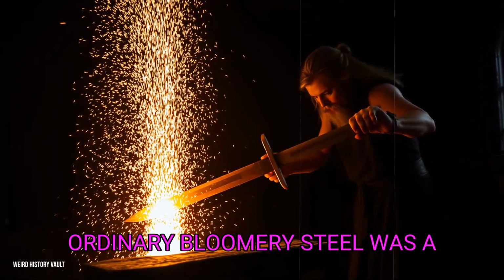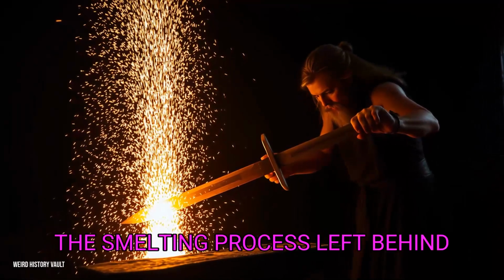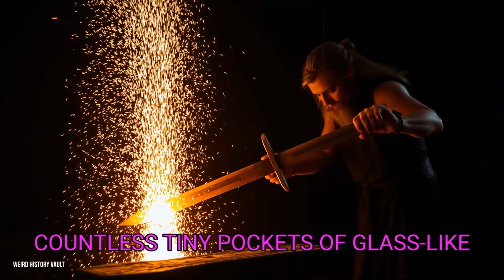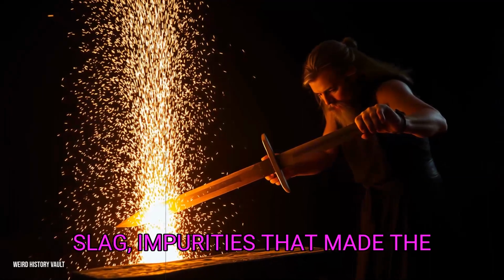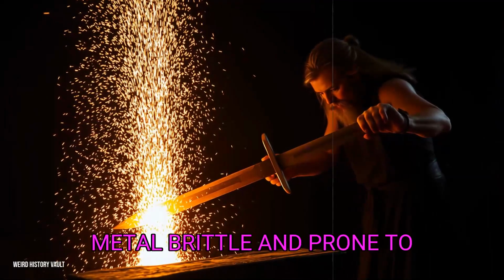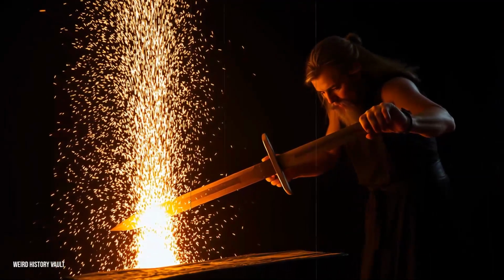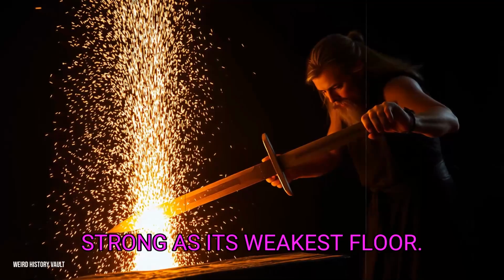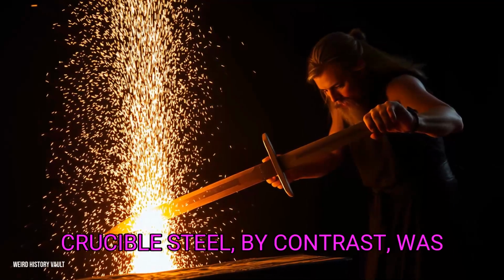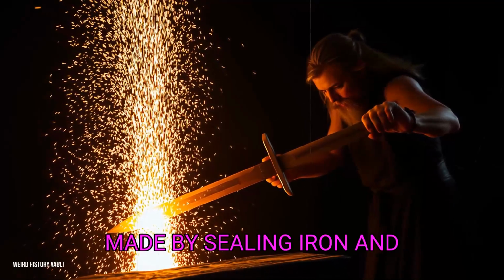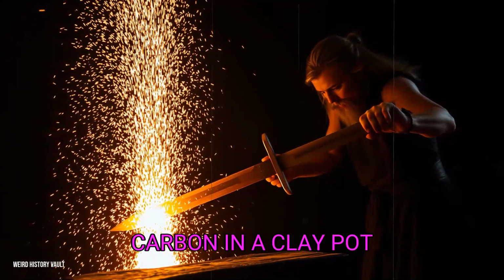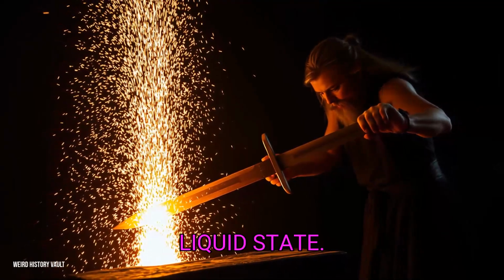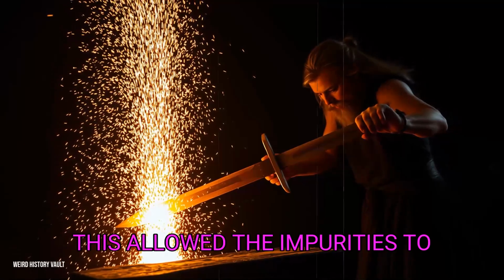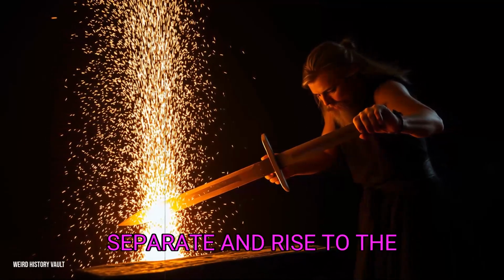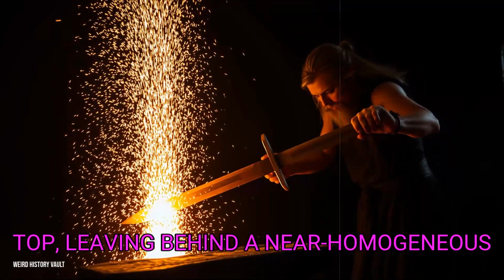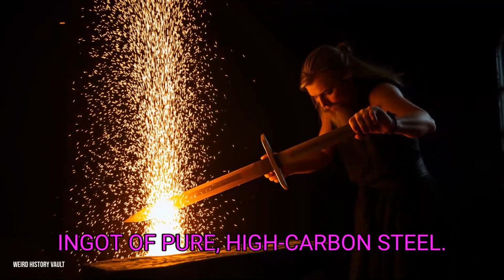Ordinary bloomery steel was a messy composite. The smelting process left behind countless tiny pockets of glass-like slag, impurities that made the metal brittle and prone to cracking under stress. A sword was only as strong as its weakest flaw. Crucible steel, by contrast, was made by sealing iron and carbon in a clay pot and melting it into a liquid state. This allowed the impurities to separate and rise to the top, leaving behind a near-homogeneous ingot of pure, high-carbon steel.